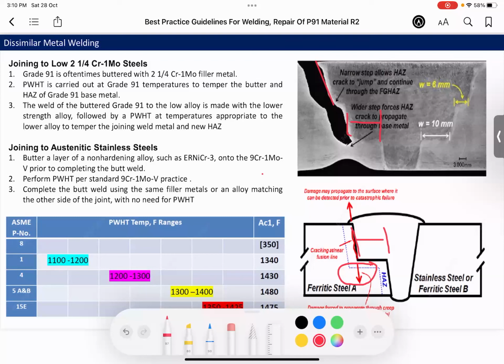and then the weld joint will be welded using P22 filler wire. For stainless steel, the weld will be done using Inconel or ERNiCr-3 on the 9Cr-1Mo-V prior to completing the butt weld joint, and then the buttering will be post-weld heat treated according to the practice for P91 material, and then complete the butt weld using the same filler wire without PWHT.